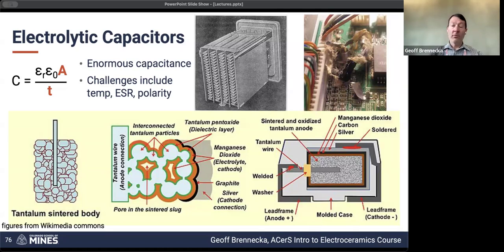So great. Now we have a very thin layer, massive area. So we have a very high capacitance. The problem then becomes, if you want to operate at high frequency, the current has to get through these tortuous paths to get current into and out of the capacitor, the storage layer. And so electrolytic capacitors often end up having relatively large equivalent series resistance values. So that's what this ESR is. So because you've got a very tortuous path that led to that very large surface area,